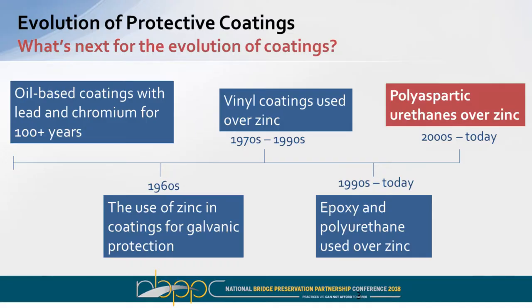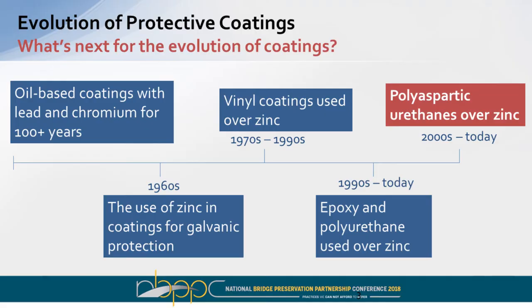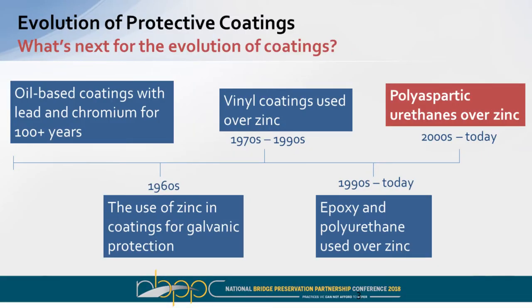Again, the problem became that those vinyl coatings have lots of volatile organic content. And so as the EPA and other regulatory bodies began to regulate that level down, that really was the nail in the coffin for vinyl coatings, at least in the bridge business. So that was somewhere in the early 1990s, when the industry transitioned to using a three-coat system of a zinc-rich primer, whether organic or inorganic, an epoxy intermediate coat, and then finished with a polyurethane top coat. And again, that's still the system of choice today for steel bridges by a vast majority of the DOTs. Back in the early 2000s, two-coat systems with polyaspartic urethane coatings really started to find their way into the market, and that'll be the topic of the discussion today.